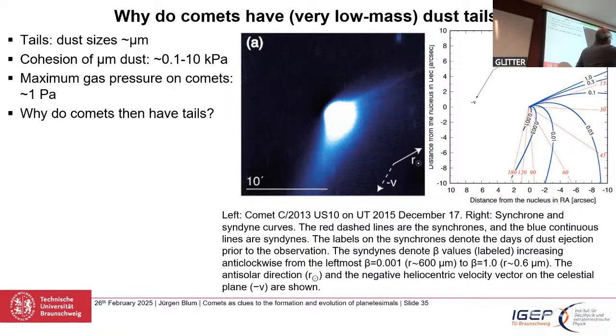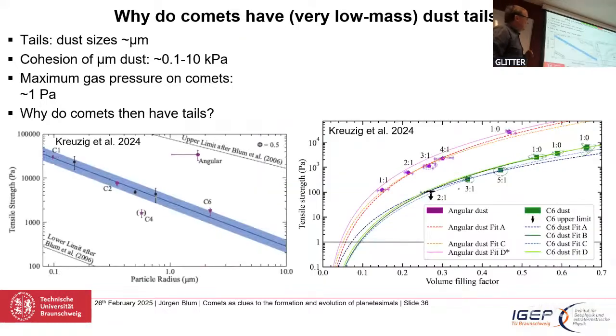Here's a cometary tail, and here are the beta values I mentioned before. So these are micron particles. Here are the particles of 10 micron, here's 100 micron. So basically, all the small particles in the tail are micrometers. And here's the trail, and here are the beta values that are very, very tiny. So these are millimeters or larger. The micron particles in the tail should possess cohesions on the order of 1 to 10 kilopascal. I show you a picture here.